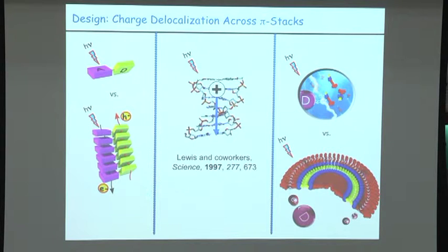Another strategy we thought of was, can we have the donor-acceptor systems non-parallel in the single molecular state, and seed them to crystallize in such a way that you get non-parallel stacks of the donor and the acceptor, wherein you can supply excess energy to the donor or the acceptor to have the charge separation, but while recombining you have a barrier because of the non-planarity in the molecule as well as in the stacks.